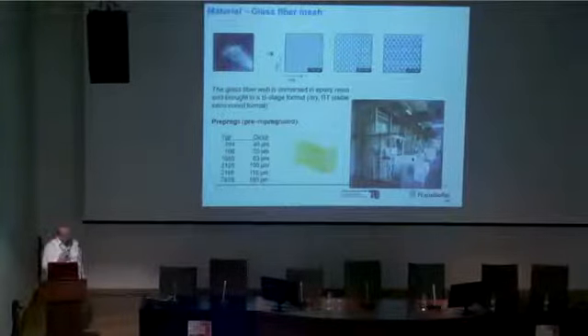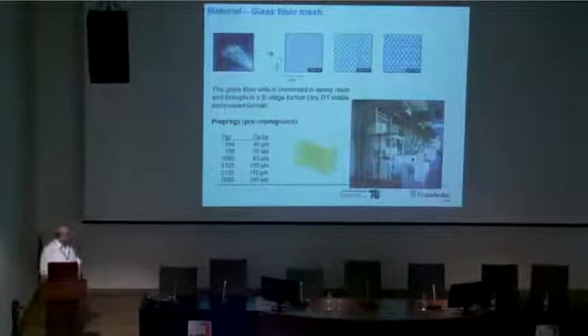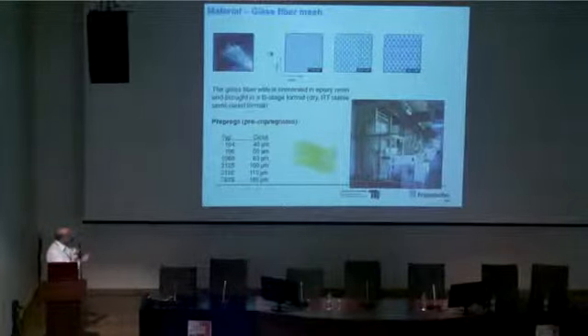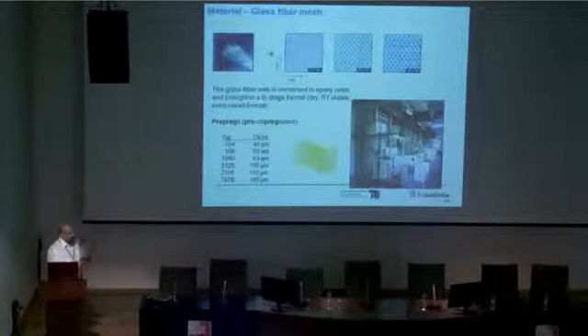So here, this foil gives you an overview of a typical FR4 manufacturing. What you get is a very intertwined web of glass fibers coming in different diameters. You can have the glass fibers in the weft and in the warp direction, and you form this very tight glass web, which is subsequently immersed in epoxy resins.